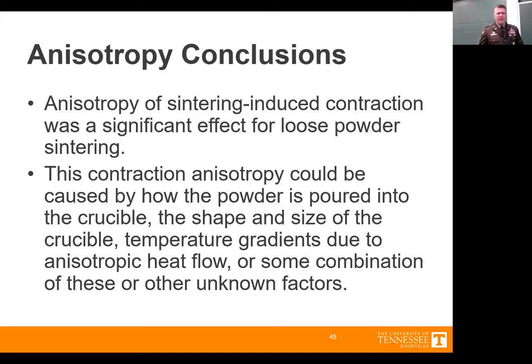Anisotropy turned out to be a very significant factor in this. It was unclear starting out whether the shrinkage would be completely isotropic and the master sintering curve would work like gangbusters, or if it was going to be a much bigger problem. The industrial data seemed to suggest that anisotropy was going to be something we were going to have to work through. It turned out to be the case.